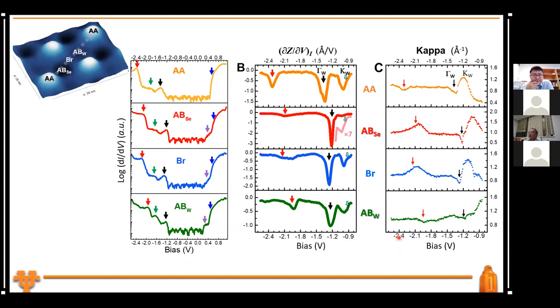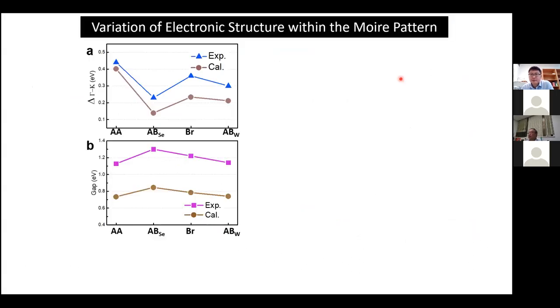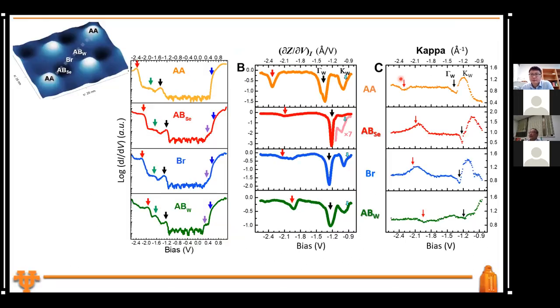Then we come and do the tunneling spectroscopy at these four different sites. And again, play the trick that we did, that we can measure where the gamma threshold is, where the K threshold is, all right? And then, okay, so you measure it. Then I bring the attention to you, like in this AA stacking, that we measure the gamma and the K separation.